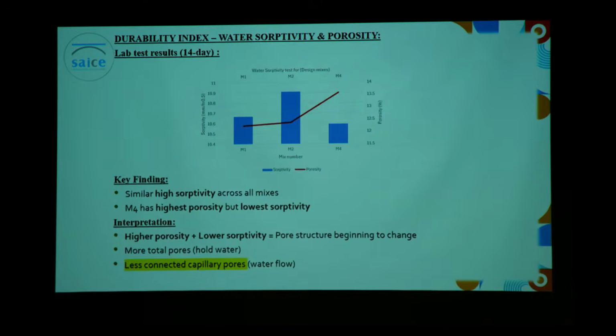The second of our indices is the water sorptivity along with the porosity. The findings here were, similar to the OPI, generally poor results, which was high sorptivity within our concrete mix itself. However, M4 had the highest porosity, however, the lowest sorptivity. And if we were to interpret this result, we'd see that due to that higher porosity and lower sorptivity, the pore structure is in a transitional state. Although it is not fully refined with those carboaluminate phases, it no longer has interconnected capillary pores. So the transmission of water is no longer being permitted within our concrete mix, within our sample.